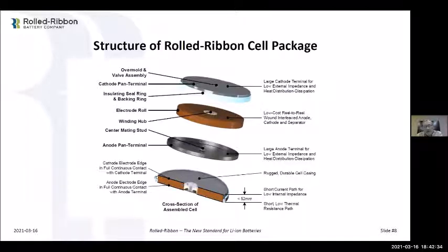So here's one cross section of one that's put together. And so you can see that the cathode electrode edge is continuous, all that edge of that spiral wind is in contact here. There is no tab in our cell. The tab is all of the edges of the electrode for the cathode and for the anode. We have a seal here, this plastic seal here, insulates between the two so that the anode and cathode don't short together. And we press that electrode roll between those two pans, and then we crimp seal this to put it all together.